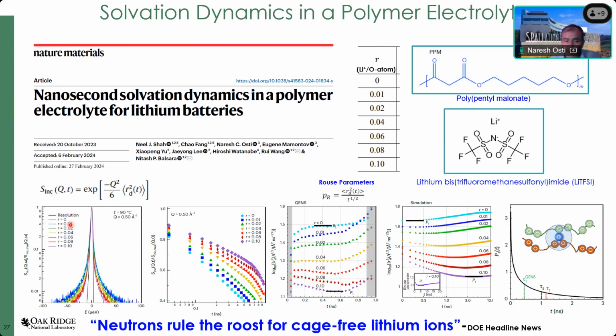Now, another beauty of this technique is you can do the Fourier transformation of this dynamic structure factor and plot it as a function of time. This is the spectra, as you can see here. This is from no salt, and then as a function of the salt. At no salt and as a function of the salt up to 0.02, you see there is a simple type of decay. But once the salt concentration is higher than 0.04, you see the pattern looks totally different compared to the pattern that you have observed in low salt concentration and no salt concentration.